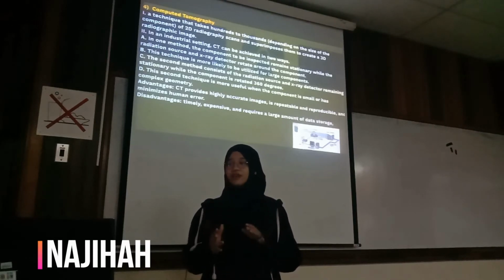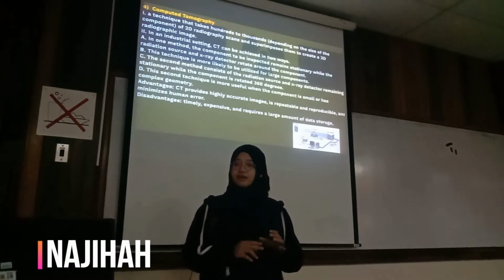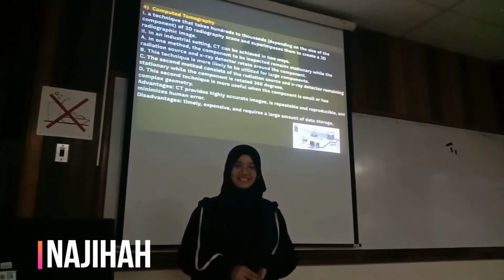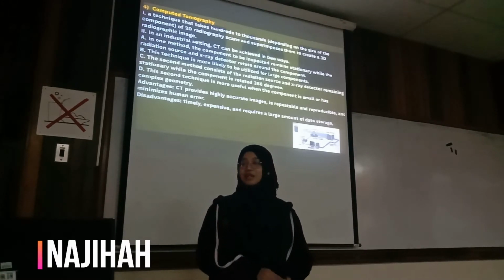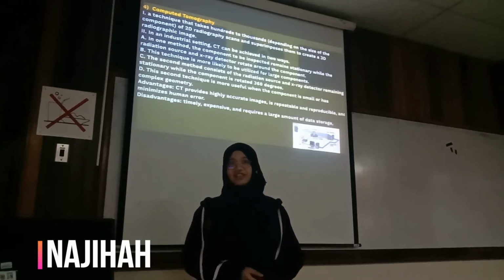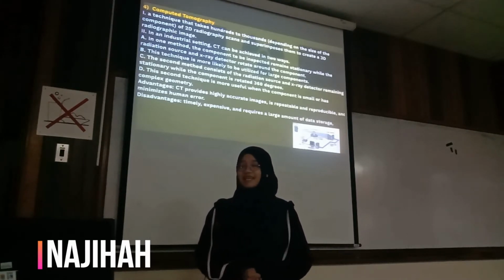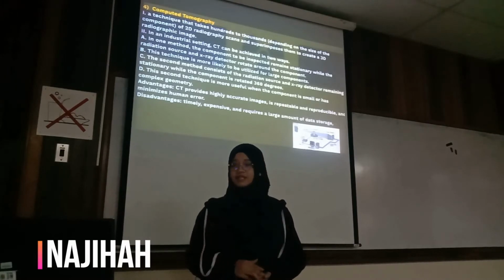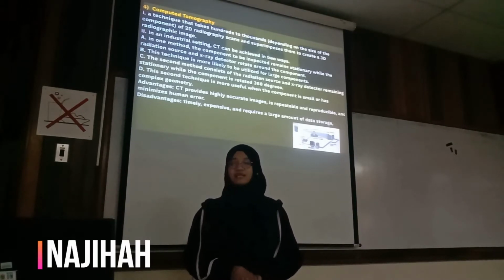which depend on the size of the component, take 2D radiography scans and superimpose them to create a 3D radiographic image. In an industrial setting, computed tomography can be achieved in two ways.